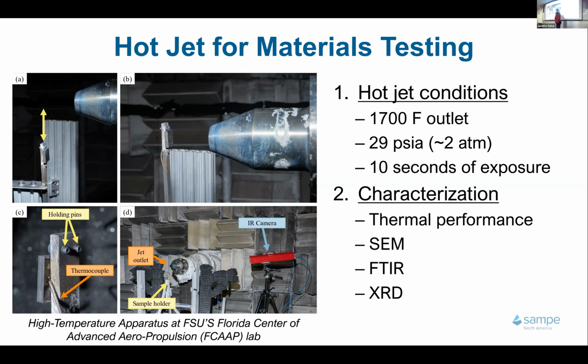Here, at the jet outlet, we have an IR camera monitoring the surface temperature. We have a thermocouple pinned on the backside of our sample, and we can track that. We also have a sample holder that, once the jet is at velocity and temperature, inserts our sample into the flow for 10 seconds and then drops it. That way we don't have any residual effects before or after.